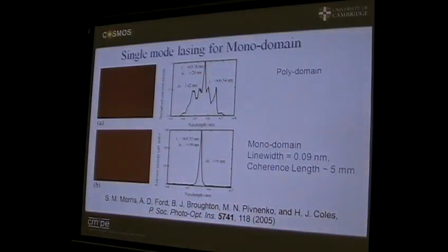Right, you've now had, I don't know, 4 or 5, 6 perhaps lectures on liquid crystals and chiral nematics. You will know that if you make a poorly aligned chiral nematic, you get a Grandjean texture. So you get planar platelets with defect oily streaks around the planar regions. Now that is horrible in a sense. You can see the colour reflection, okay? But it actually gives you an interesting way of getting many laser lines.